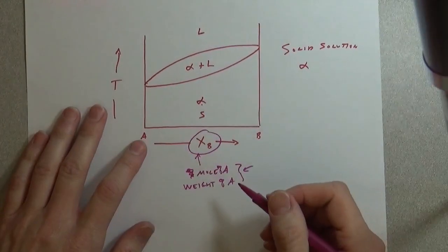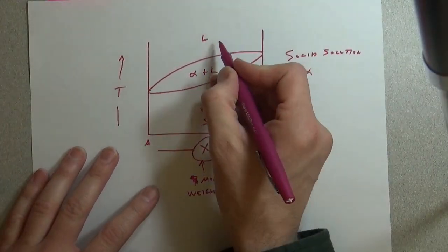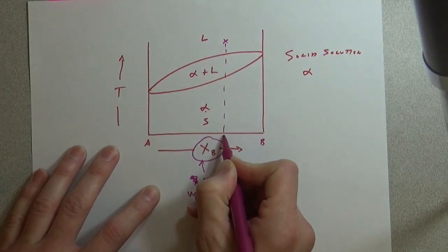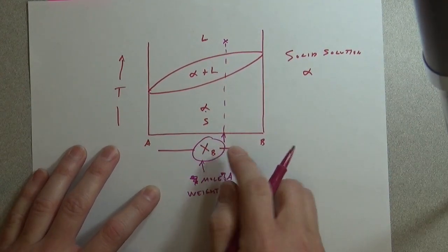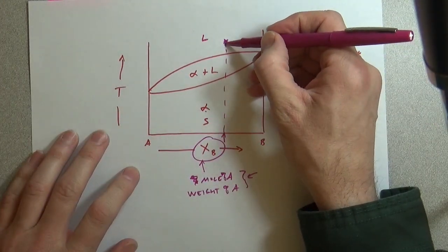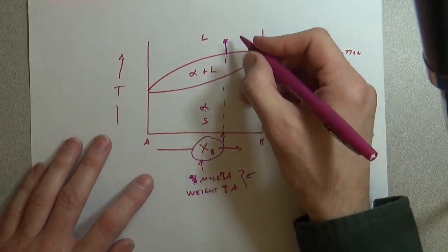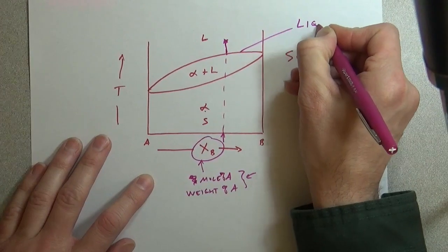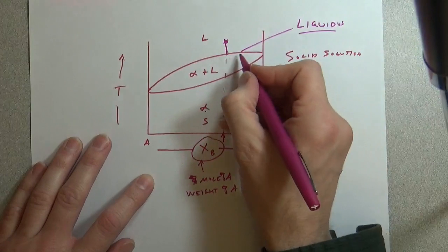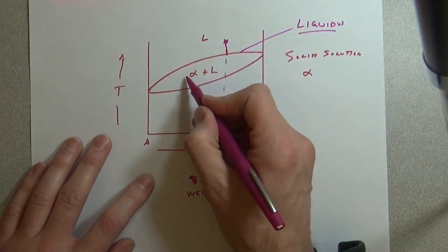So this is our phase diagram, and we can think of it again just the way it was before. If we start up here at some composition, and we're at high enough temperature, we have liquid, great. Come down here. At this point, we cross what's called the liquidus line, L-I-Q. That liquidus line is the separation between being all liquid and first starting to form a solid.